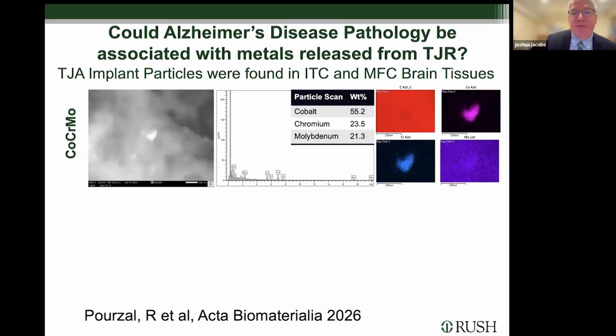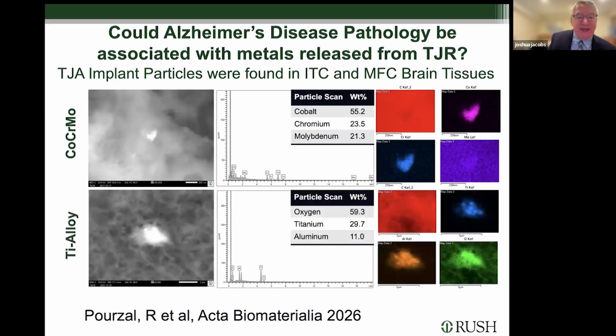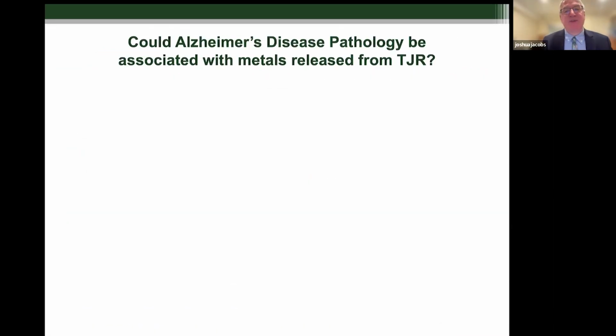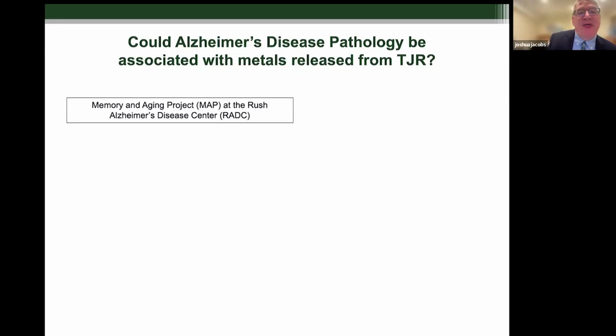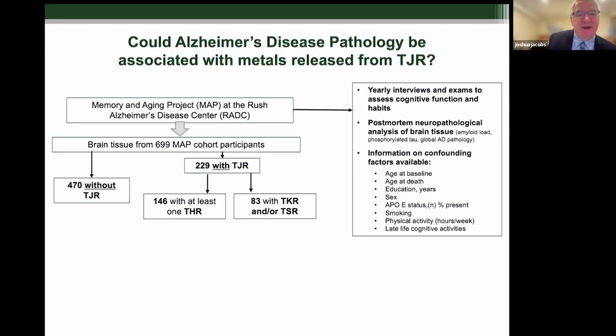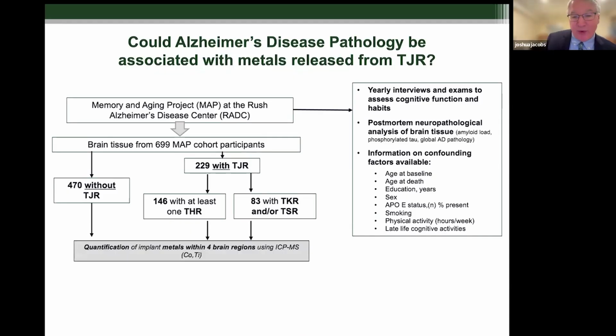And this is hot off the press. Can these metal particles cross the blood-brain barrier? It turns out they can. We've shown this for cobalt chrome debris, also for titanium alloy debris. In most hip replacements and knee replacements, one of the components is made from titanium. This we just reported in the journal Acta Biomaterialia. We looked at this issue in some depth because we have an Alzheimer's Disease Center at Rush that really does an amazing job of getting patients, following them longitudinally, and having their brains to look at after death.